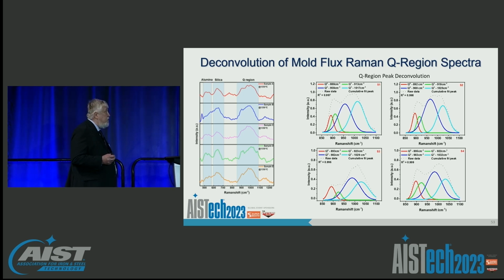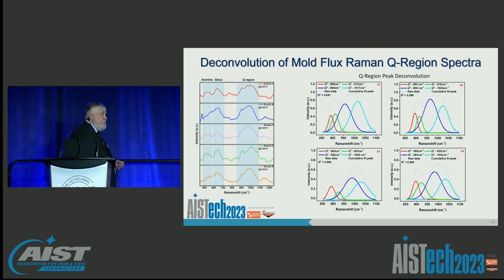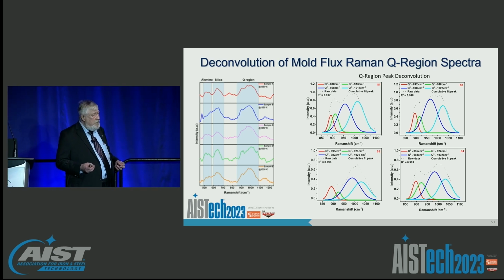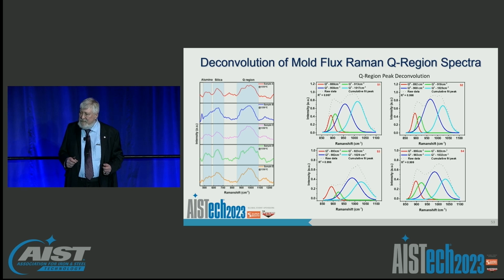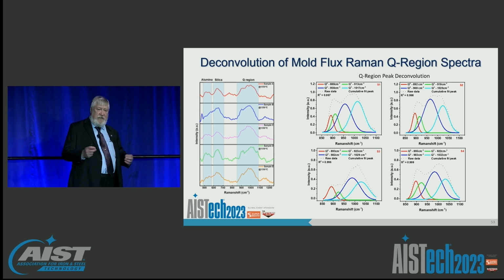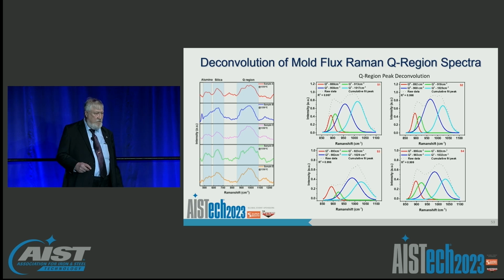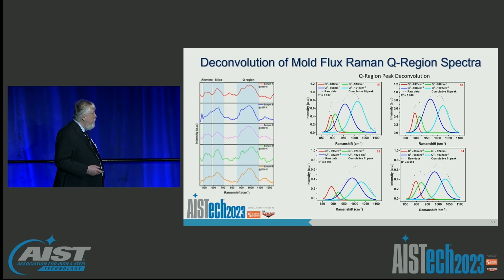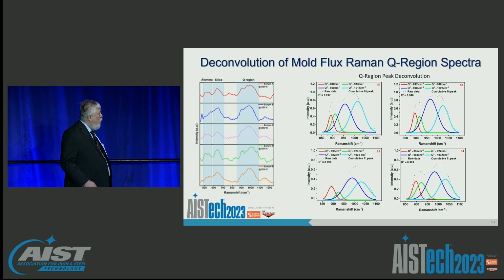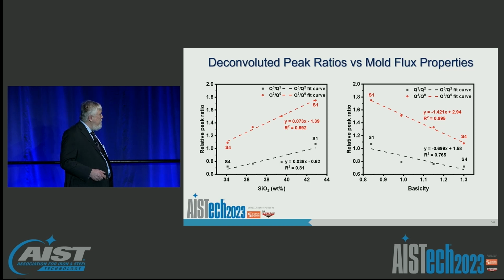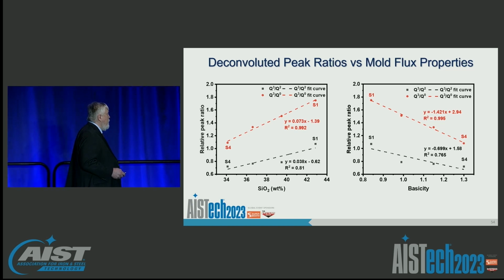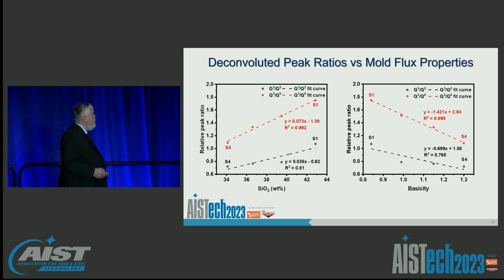Those fundamental components can actually be used to not only calculate the composition of the flux, but they can also do things like estimate viscosity of the flux, because it's the polymeric state of the slag systems that actually correlate to the flux viscosity. And so we've been able to correlate a lot of these things, and this is work that we've done on the spectra deconvolution in the flux systems. And we're also now correlating those compositions and basicities of these fluxes to the structure based on the ratios of the Raman spectra peaks that are deconvoluted.